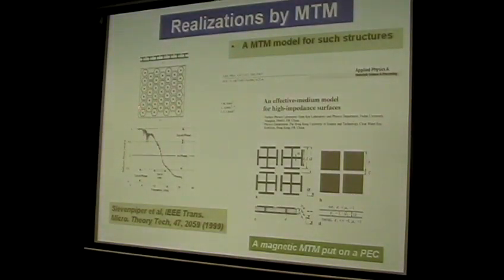Actually, this famous structure appeared before the concept of metamaterials. Dr. Dan Sievenpiper from Eli Yablonovitch's group proposed a famous structure called the mushroom structure. He found that the reflection phase can change continuously from pi to -pi. So therefore, there must be a frequency at which the reflection phase is exactly 0.